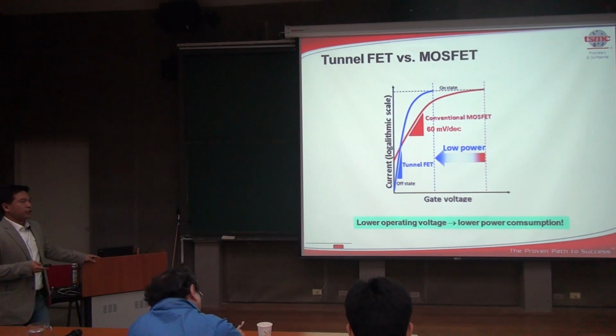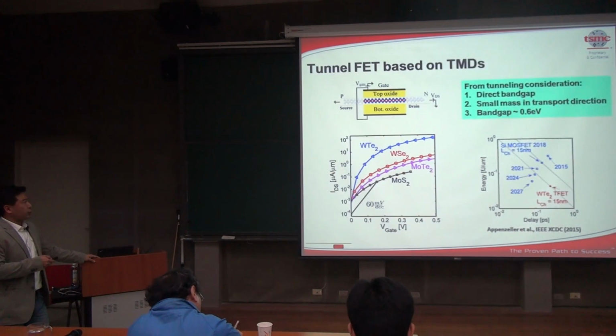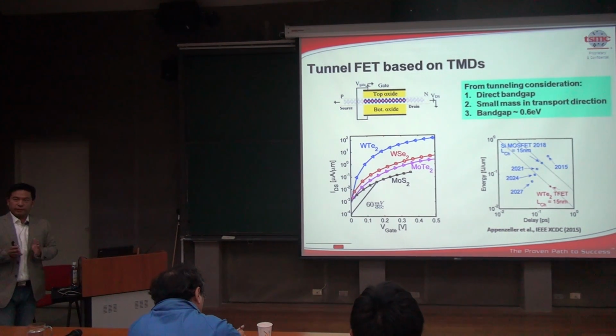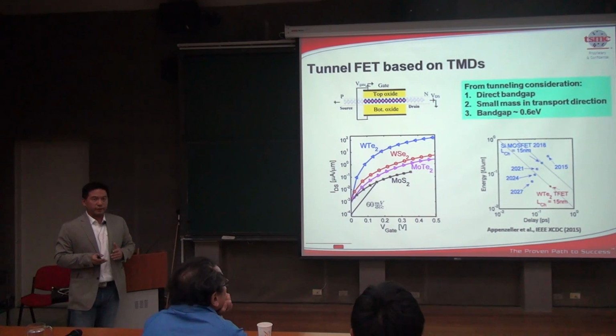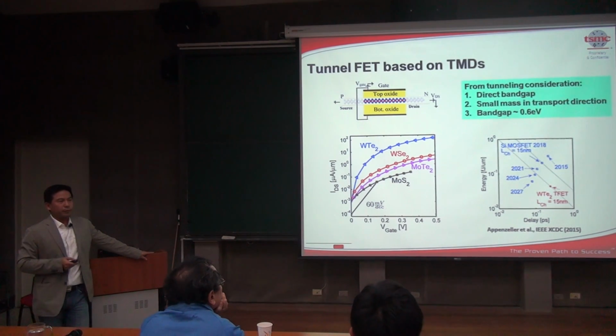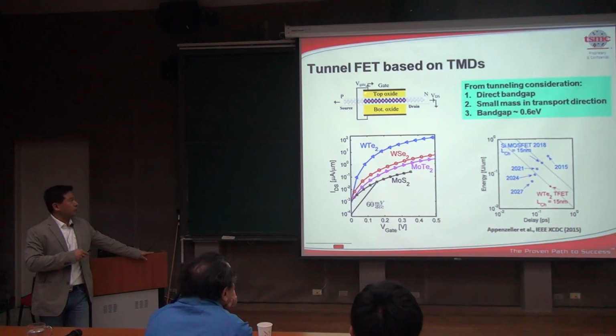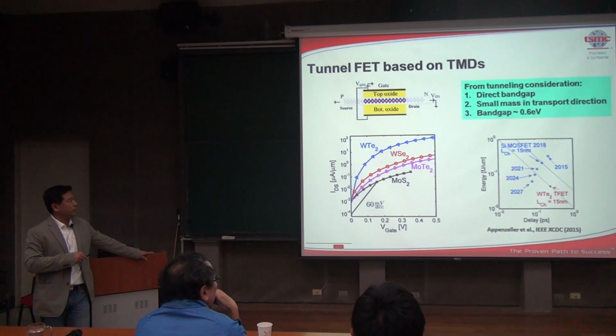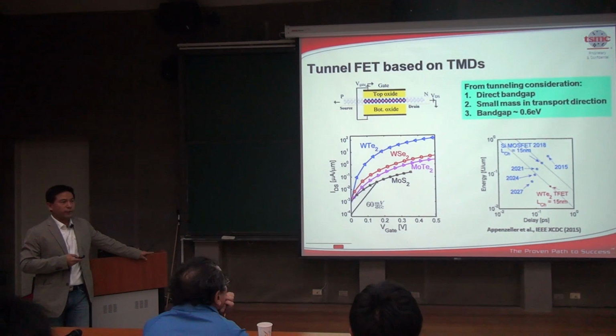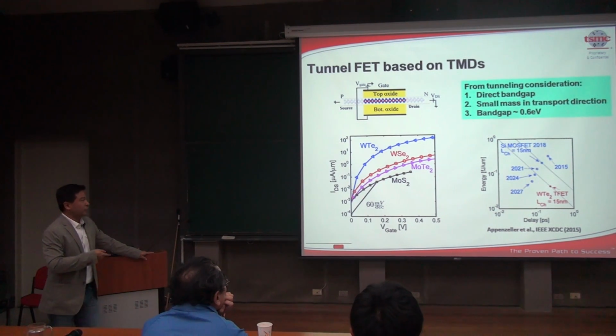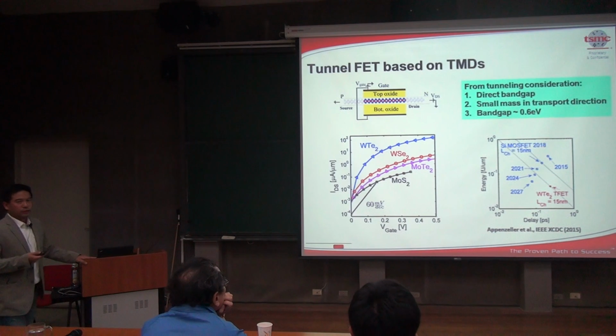And what kind of features are needed for this tunnel FET to work? It actually requires very good electrostatic control. So again, with 2D materials, the benefit is that the body thickness is atomically thin, so you can enable, in principle, the best electrostatic control you could have. You could have P-type doping on the source side and N-type doping on the drain, respectively. And with very good electrostatic control, you can have an operating tunnel FET. With 3D materials, in principle, you can also create a tunnel FET, but when you thin down the body thickness, you suffer from mobility degradation and also a lot of trap charges.